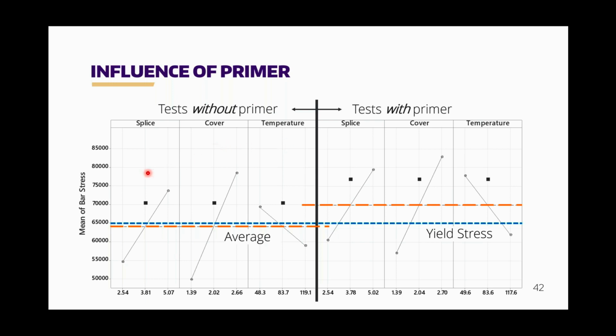What you can see is what you would expect. As splice increased from left to right, you get an increase in the bar stress before failure. If you increase cover, you also get an increase. And with temperature, as you increase temperature, you get a decrease in strength. So the trends all make sense, and that's good to have. The next thing is comparing tests without primer to tests with primer. You can see that there's a shift in the average stress, and that shift is about 10%. You can also see that it shifts the stress to be above the yield stress.